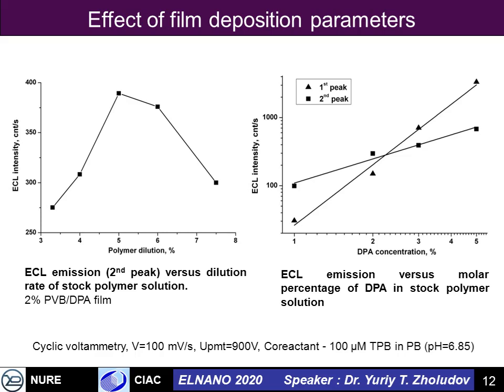Also, the content of fluorophore per matrix molecules of PVB is important. On the right picture it is clearly seen that increasing the concentration of diphenylanthracene in the polymer from 1 to 5% gives a very strong increase of two ECL peaks, but at different slopes. The first peak increases more drastically, especially taking into account that the ECL intensity is given on a logarithmic scale.